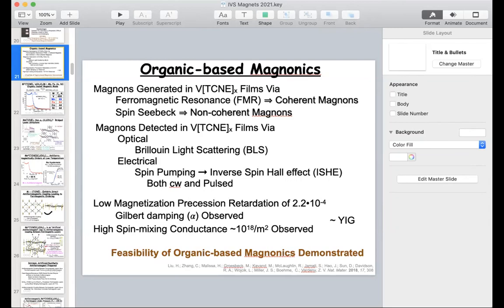So do you see any relationship between the domain size and the crystallinity? No, we've not studied domain size and crystallinity, but it's well known that if you take nickel metal, which is a crystalline material and magnetically ordered as a ferromagnet, you can melt it and quench cool it into liquid nitrogen and you'll get amorphous nickel, and that amorphous nickel will also be a ferromagnet. It will not be as magnetic as the crystalline material, and the ordering critical temperature will be lower, but it will still magnetically order, suggesting magnetic domains are sufficient to support magnetic ordering, but not as good as if you could make a crystalline material. And we've always been interested in trying to make the crystalline vanadium TCNE, arguing it should be better, but we have not achieved that.